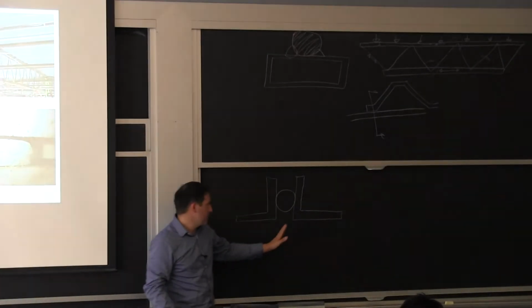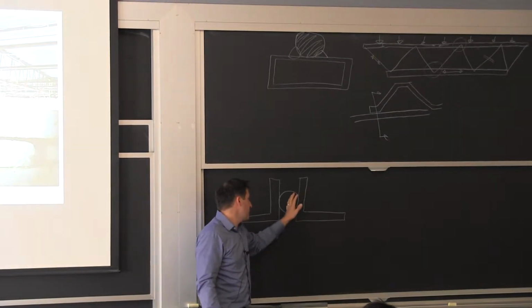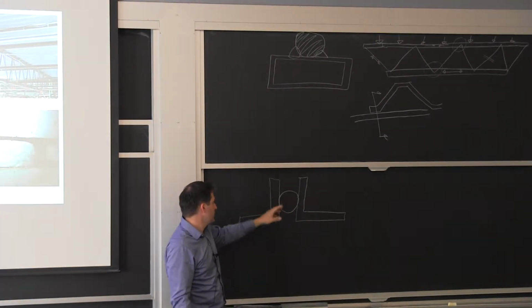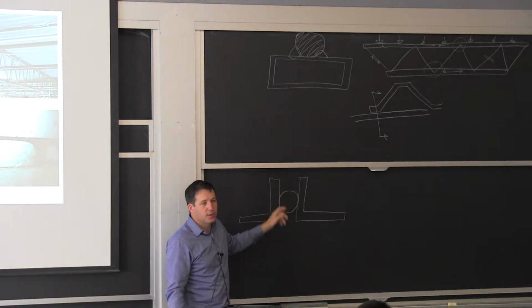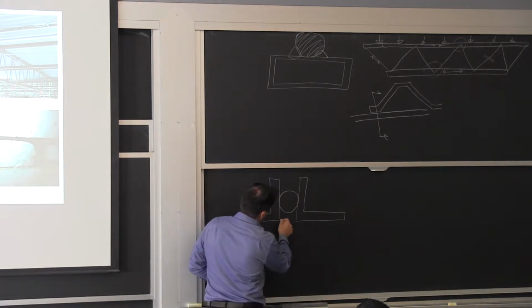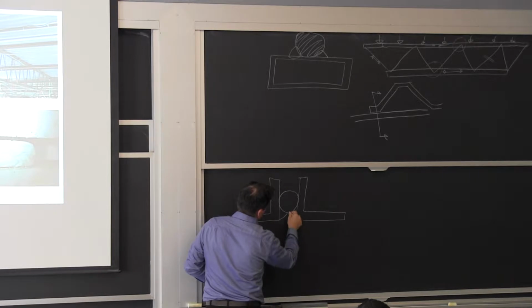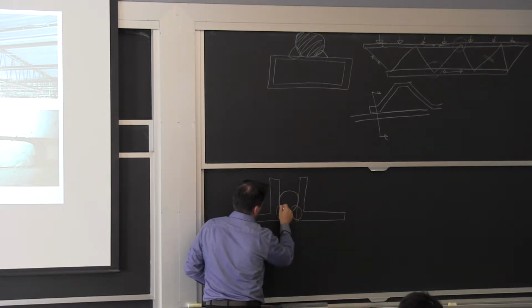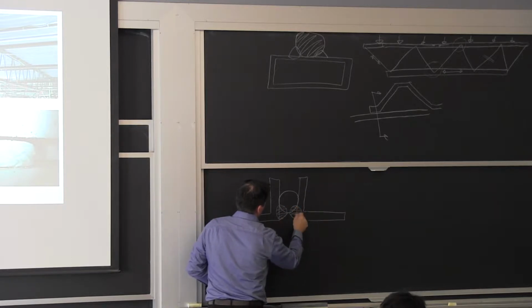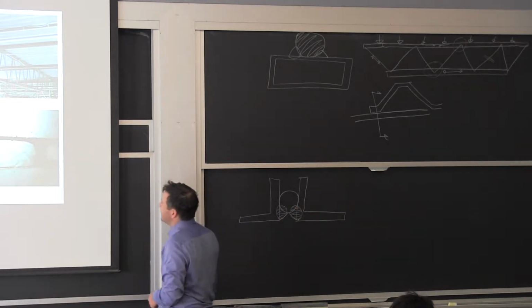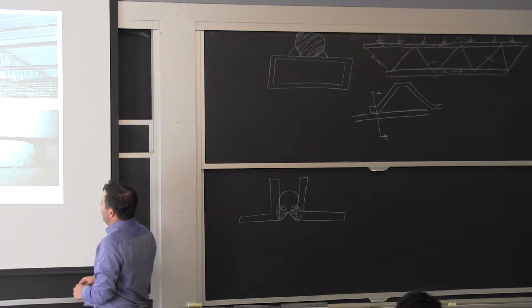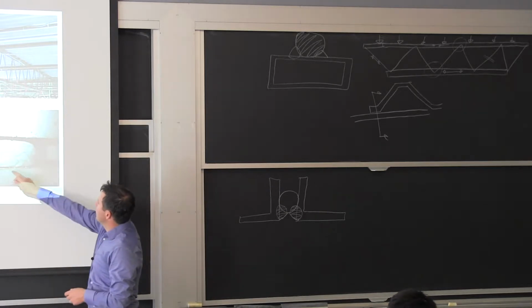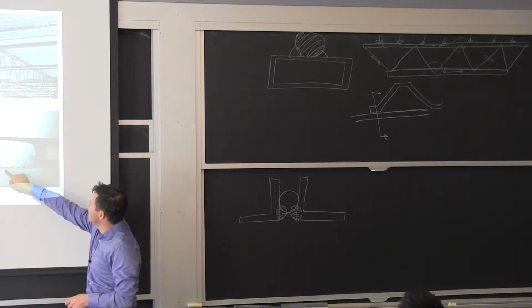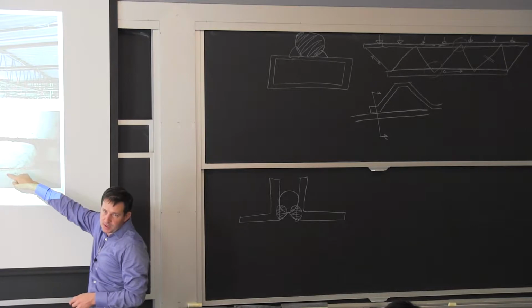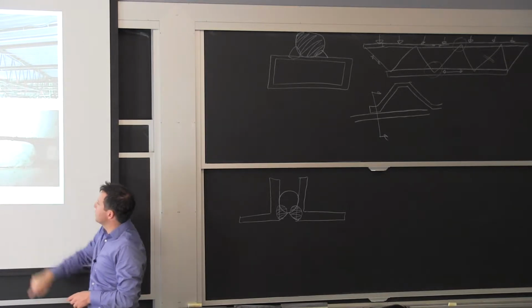The way they build it is they have a rig, they put this side, they put the round bar diagonals, and then they put the other one, and they come from under, and they try to do these welds here, and they try to fuse this whole zone. And that is your fabricated joist. What you can see from looking from under here is there is a gap between the angle bar and the weld.